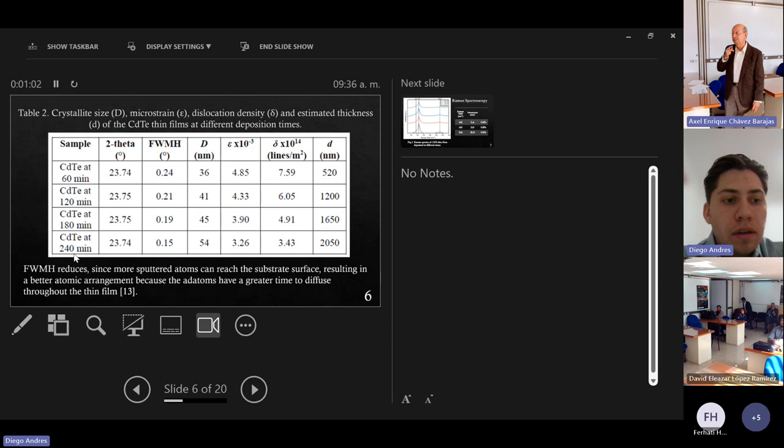Yes, we can increase the time for the thin film deposition. But since we are looking to create semi-transparent thin films to have a double use as photovoltaic windows, increasing that time would mean that transmittance would be lower and absorption would be higher. That means we would have opaque windows instead of semi-transparent. So that's why we opted for a deposition time between 60 minutes and 240 minutes, because